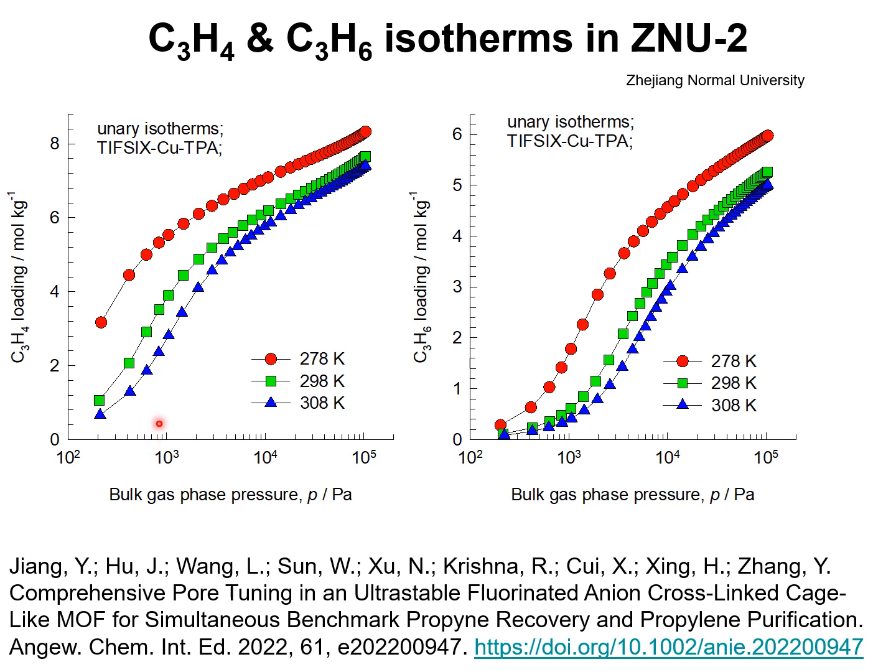The data for both components show isotherm inflections, and certainly for propyne, the isotherms are also rather steep, and the single site Langmuir model fails to capture the isotherms for both guest species.